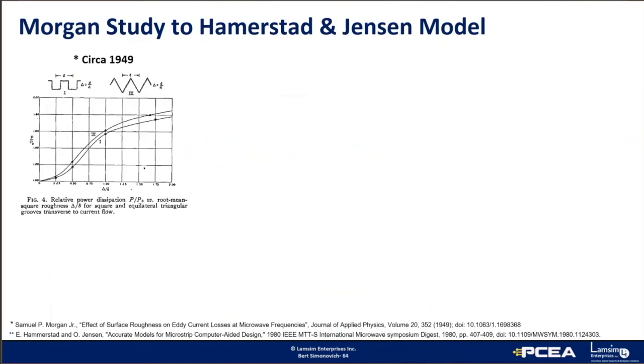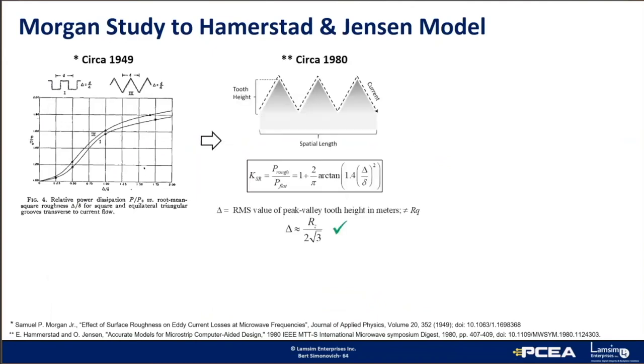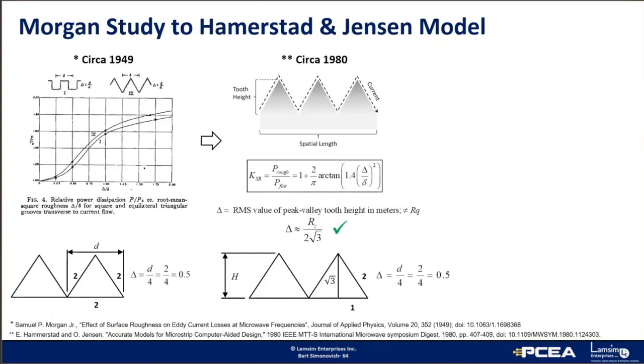In 1949, S.P. Morgan pioneered the modeling of surface roughness using square and triangular grooves. He later published a paper showing the relative power dissipation for different values of RMS roughness to skin depth. In 1980, Hammerstad and Jensen did some further study and proposed an empirical fit formula for calculating Ksr based on Morgan's equilateral triangle results. In this equation, delta is the RMS value of the peak-to-valley tooth height. It's not the same as RMS Rq found in the datasheets. Instead, you can use my triangular roughness model I described in the previous slide using Rz. And here we can compare Morgan's equation to determine RMS delta versus my triangular roughness equation. We see they're the same thing.